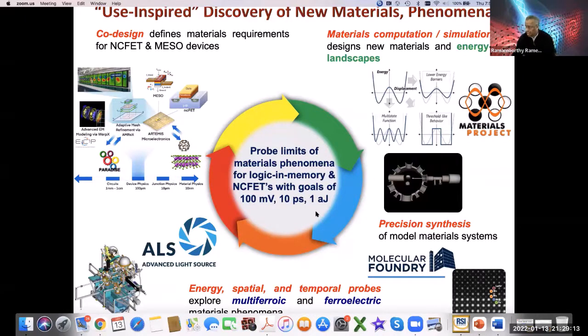We showed in one piece of work, it was just goofy research, nothing practical, I think, we had a whole bunch of domain walls, and it turns out that the open circuit voltage scaled with the number of domain walls. So you could get 15 volts open circuit voltage, but the short circuit current was really small. If you look at silicon, it's about 50 to 100 milliamps per square. Oh, I'm mixing up my units, Astita. It's orders of magnitude smaller, mainly because the short circuit current is really small.